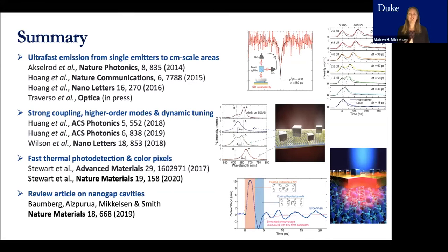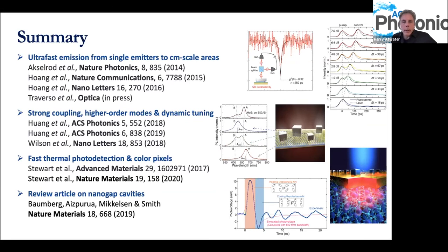We did actually also observe it for single emitters, I believe. We saw modifications in the fluorescence spectrums with double peaks, as well as in the plasmon resonance. That was a little bit harder to model because we wouldn't quite expect that from our geometries. We never published that because we couldn't quite figure out what was going on. But thinking back, I think what's going on is likely some small atomic protrusion, small variation, that's allowing us to get even larger hotspots than you would expect from this idealized planar structure. And in those cases, we can get into the strong coupling regime, likely for single emitters as well. Yeah.